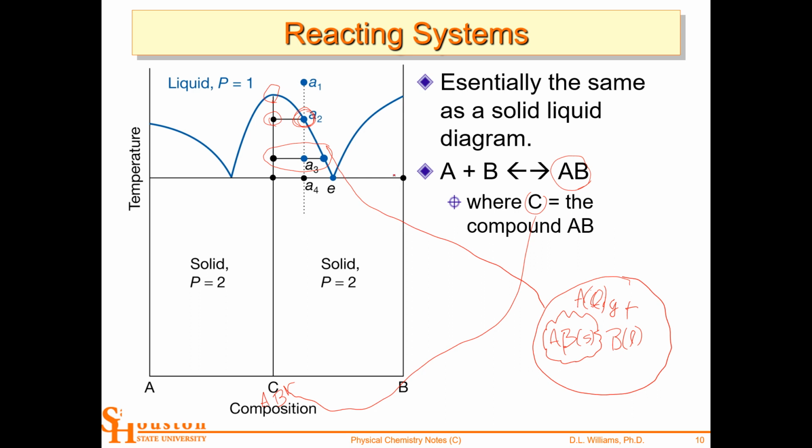And so eventually down here, you have this picture, let's draw it right here, of some AB solid grains and then B solid around it. And you would see that in a micrograph. If you took that solid then and you sliced it, polished it, looked at it under a microscope, used polarized light or whatever, however you could see the different grains, you would see chunks of AB that had precipitated out and then B that had frozen around it and held it together.